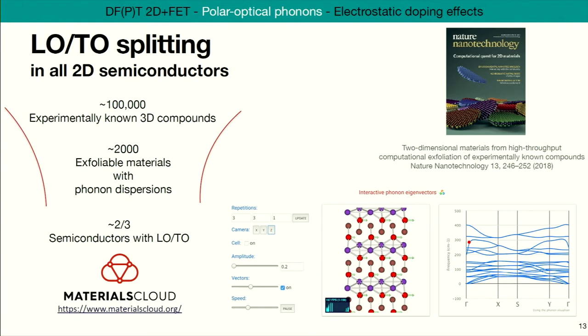All right, so why is this important? I already mentioned it, but this came around when we were doing this project of trying to find all 2D materials that could be exfoliated from experimentally known 3D materials. And so we made this database and computed the phonons, and about two-thirds of those exfoliable materials are semiconductors, and all of those have LO-TO splitting. So if you go on this database and click on a random material, there's a very good chance that you'll end up seeing those characteristic sharp variations of the dispersion with some LO-TO splitting.